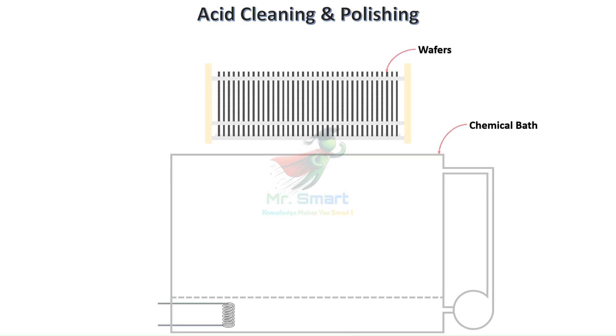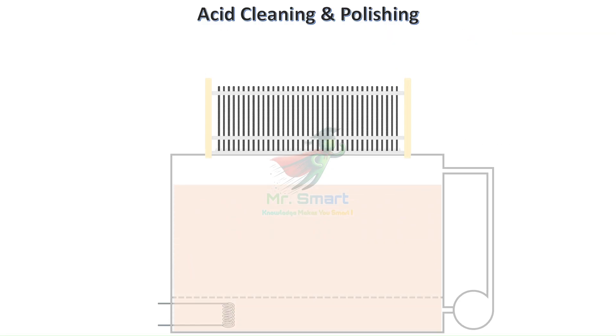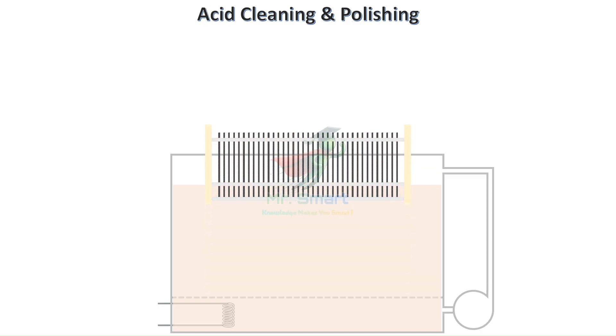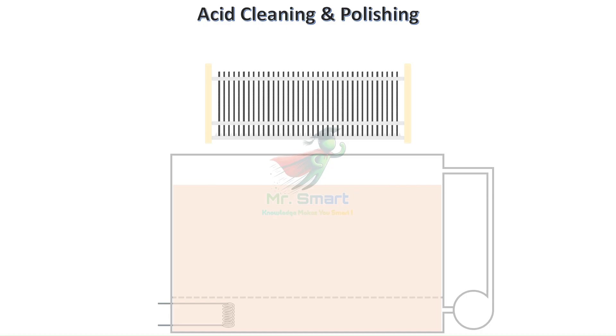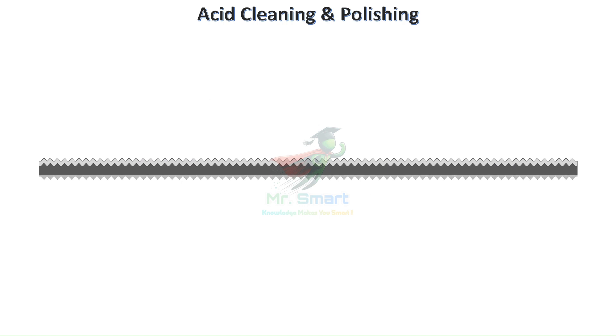The acid cleaning process is technically called polishing. Using hydrogen fluoride (HF), we etch away oxidized silicon layers, while hydrogen chloride (HCl) removes metallic residues by absorbing them into chloride compounds. Following etching, wafers undergo a second thorough washing to remove etching residues. This step ensures absolute cleanliness before applying the anti-reflective coating, maintaining the pristine surface quality essential for optimal performance.